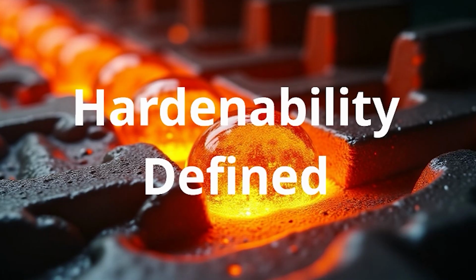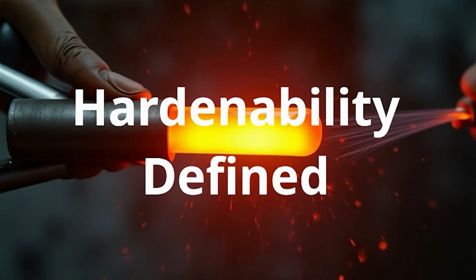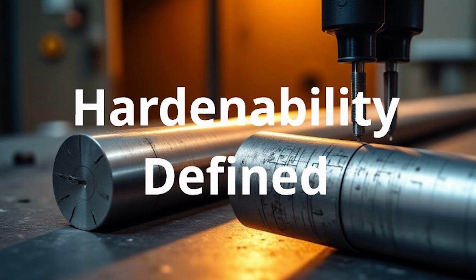The Jominy end quench test is the standard method for measuring this. It involves heating a cylindrical steel sample until it's fully austenitic, then quenching one end with a standardized water spray setup. This creates a controlled cooling rate that decreases as you move up the sample. Hardness measurements taken at regular intervals create a hardenability curve.